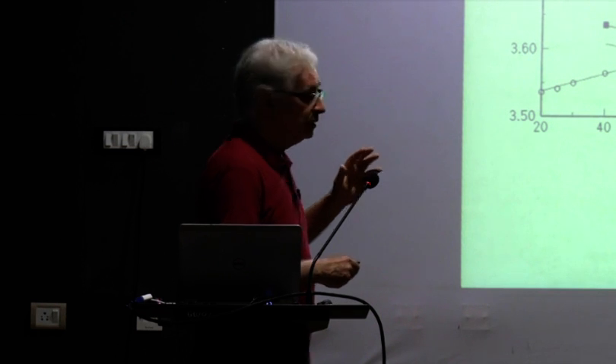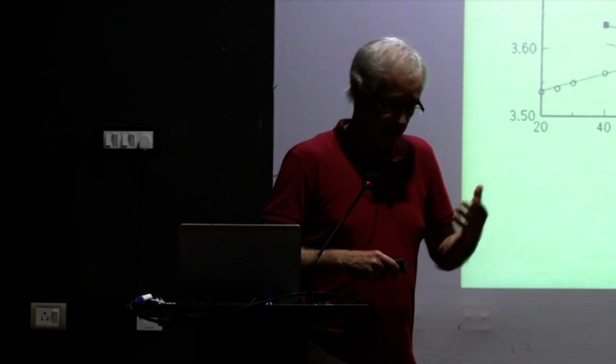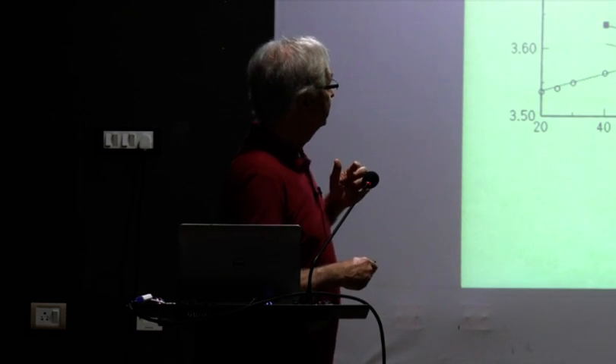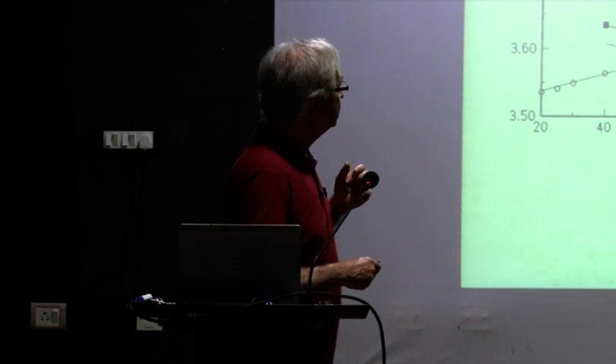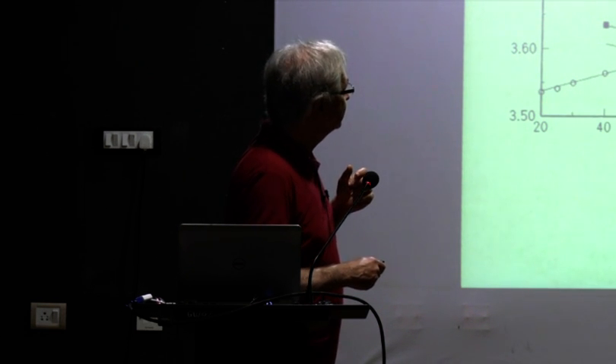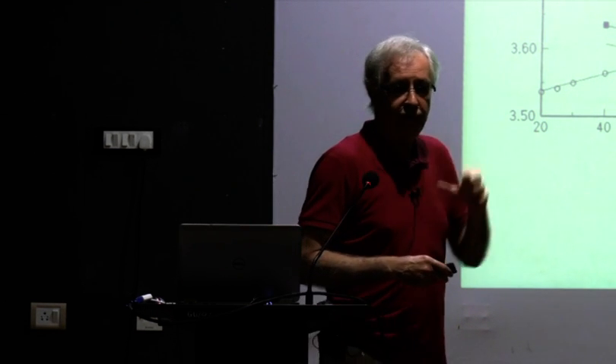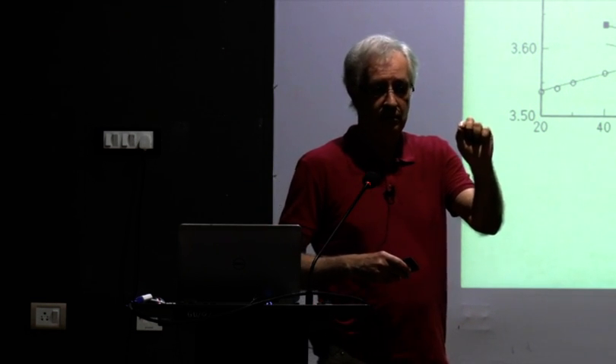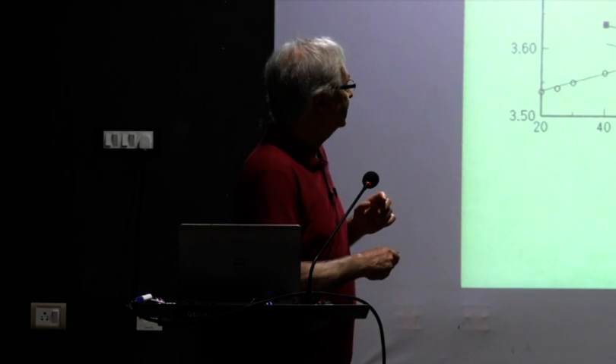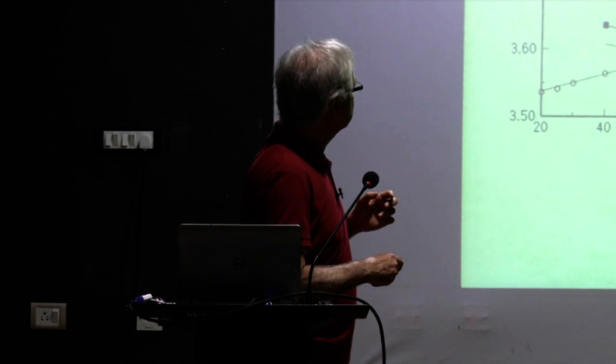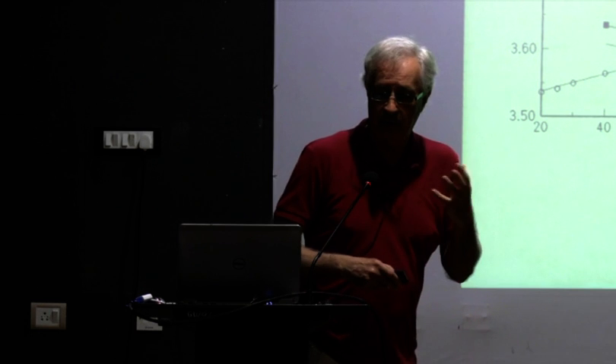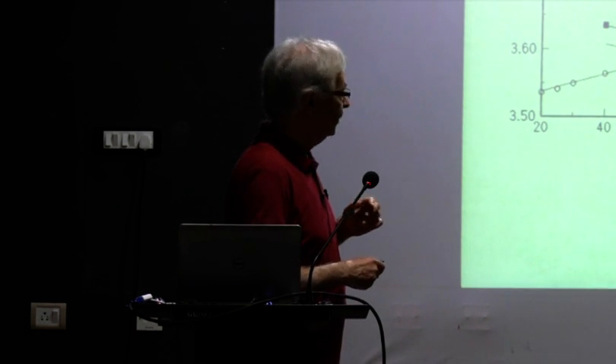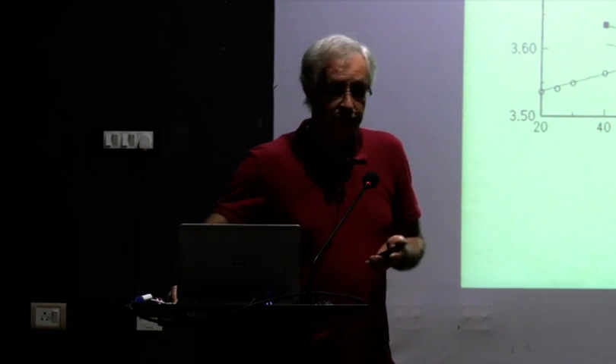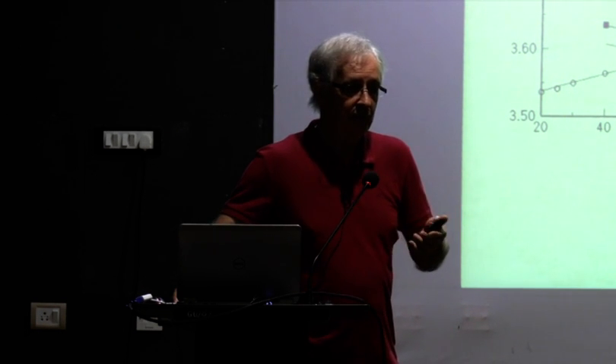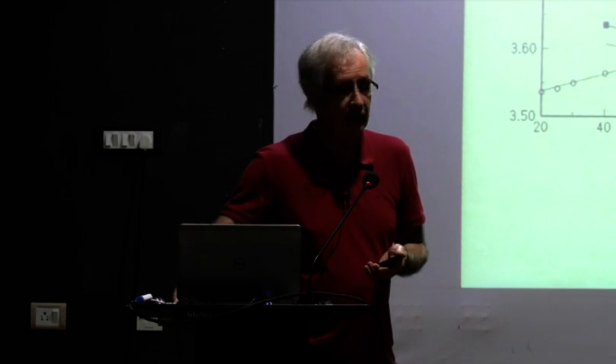Other than bringing the FCC iron onto substrates, you can also check and see what FCC iron is doing in other environments. This here is Fe4N, iron 4 nitrogen. Iron 4 nitrogen is basically FCC iron with a nitrogen atom in the middle. The electronic properties are a little bit different, but it has expanded the lattice so much, and if you look at the hyperfine field, you see that it sits over here. I haven't labeled this for some reason, I forgot, but this was another material where you also had FCC iron in a certain environment. So this is another experimental evidence that you have the antiferromagnetic to ferromagnetic transition in iron.